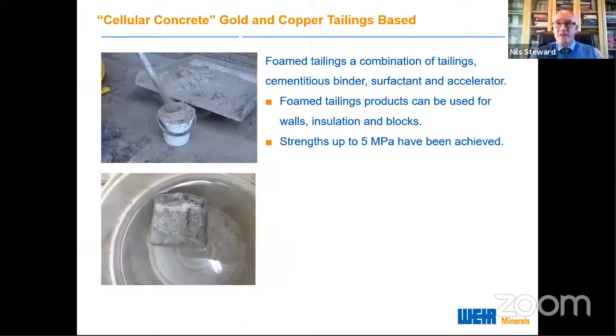In terms of cellular concrete, again, one of the tasks that we were set was to be able to produce a barrier to fire underground. And typically what was used was concrete foam blocks that were actually carried underground and used to block off various haulages. We were able to manufacture a sprayed cellular product. So it's just tailings, surfactant, and cementitious binders. And we actually sprayed it through a nozzle with the accelerator at the end, and we're able to spray it